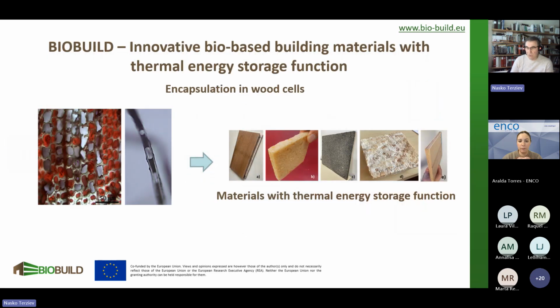The second moment, what is also pretty characteristic, is that the phase change materials, which are also biological materials, function pretty well when they are encapsulated in something very small. Normally, a big volume of the material will also function, but then we have to wait a pretty long time for it to melt or solidify. But if you have it encapsulated in something small, like in our case, on the left side you see the structure of the wood. If we can encapsulate it in the red spots here, or in a single fiber, it will react much, much faster, which means we can gain more energy by faster transition from melting to solidification. So this is the main idea, and this should be implemented in various materials.